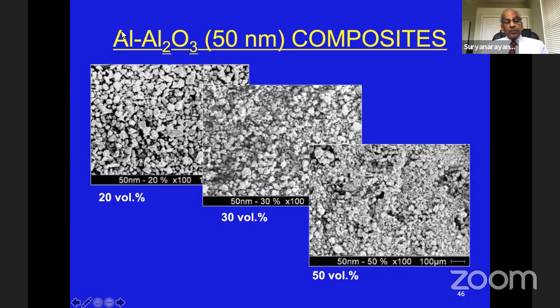So what we started with was the alumina system. The alumina particles are 50 nanometers. And we said, let's take 20%, 30%, or 50% by volume of alumina and see whether we can distribute it uniformly by mechanical alloying. And what we see is you can produce very uniform distribution of alumina in the aluminum matrix by increasing the milling time to approximately 20 to 24 hours. And it is very uniform. And this is confirmed by EDS mapping technique.